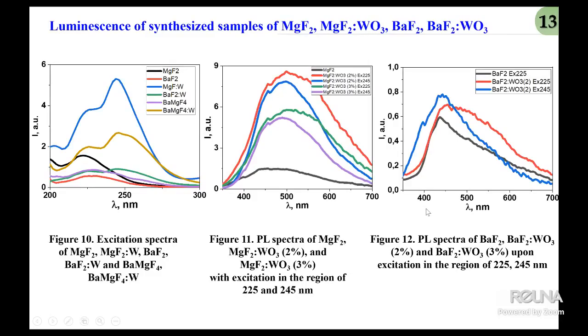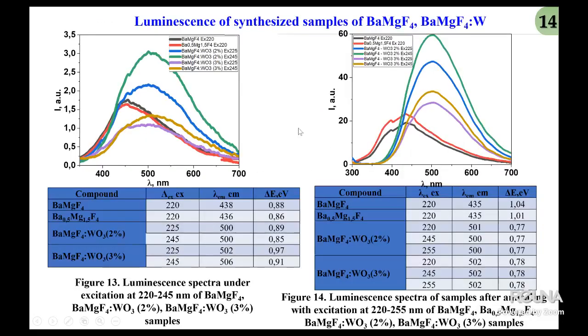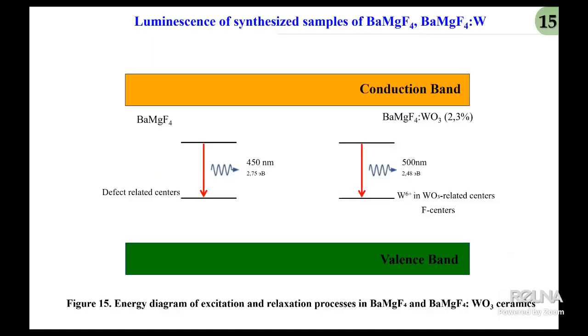Figure 12 shows the photoluminescence spectra of BaF2 with tungsten. This slide shows luminescence spectra and the excitation spectra, from 220 to 245 nanometers. This mechanism